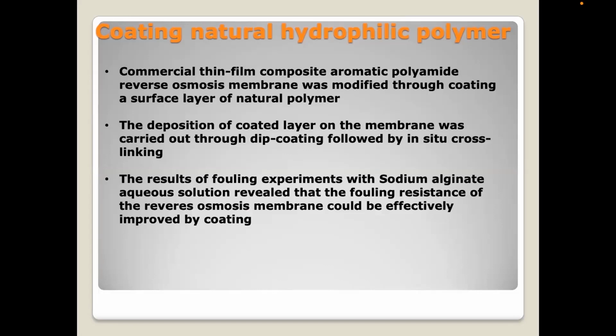Coating with a natural hydrophilic polymer. The commercial thin film composite aromatic polyamide reverse osmosis membrane was modified by coating a surface layer of natural polymer. The deposition of the coated layer on the membrane was carried out through dip coating followed by in situ cross-linking. The results of the fouling experiment with sodium alginate aqueous solution reveal that the fouling resistance of the reverse osmosis membrane could be effectively improved by coating. For that, we adapted coating on the RO membrane.